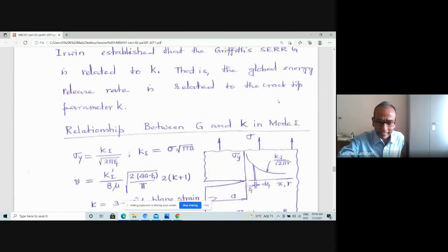So the question is that you must establish how this K is related to the strain energy release rate of Griffith. That strain energy release rate of Griffith is nothing but 2 gamma S per unit crack area. Therefore, that should also be established. So the Griffith energy release rate has got to be calculated from the stress field that was determined by Irwin. He did, and fortunately he cracked that, and showed that yes, this K, which reaches a critical value at the onset of crack extension, indeed also ensures availability of the critical energy for the creation of new surface that has been given by Griffith.